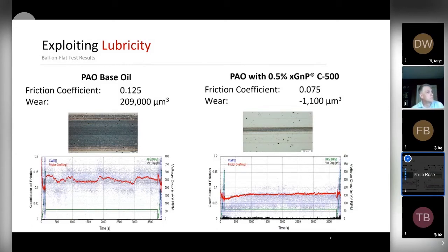So the data on this slide are really the results of a customer trial using C500, which is one of our graphene nanoplatelets produced using our mechanical exfoliation process. The data are ball on flat test results for a polyalpha olefin-based oil with and without graphene nanoplatelets. You can see that the incorporation of low levels of C500 greatly reduces the friction coefficient and improves the wear performance.